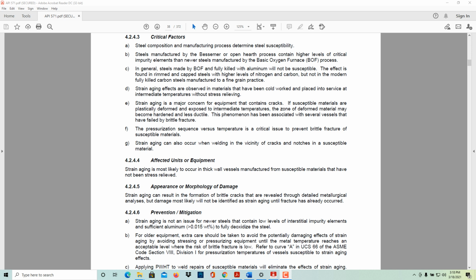Critical factors. Steel composition and manufacturing process determine steel susceptibility. Steel manufactured by the Bessemer or open hearth process contains higher levels of critical impurity elements than newer steel manufactured by the basic oxygen furnace process. In general, steels made by BOF and fully killed with aluminum are not susceptible. This effect is found in rimmed and capped steels with higher levels of nitrogen and carbon, but not in the modern fully killed carbon steels manufactured to a fine grain practice.